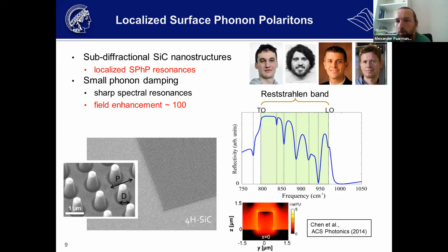There are these monopole modes, which have a significant interpillar coupling. So these are not only localized modes, but sort of collective modes of the whole structure. And these are these dips here. Then there are dipolar modes, which are different excitations with the dipole in plane, left and right of the pillar sides. These are at higher frequency.